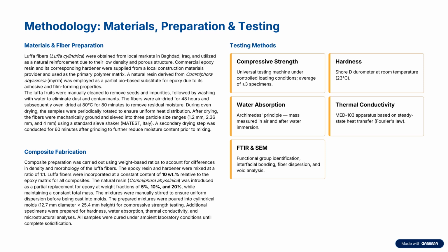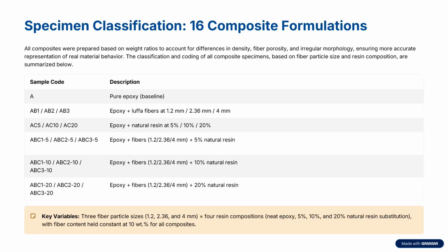Additional specimens were prepared for hardness, water absorption, thermal conductivity, and microstructural analysis. All samples were cured under ambient laboratory conditions until complete solidification. For that, we test compressive strength, hardness, water absorption, thermal conductivity, and SEM. All composites were prepared based on weight ratio to account for differences in density, fiber porosity, and irregular morphology, ensuring a more accurate representation of real material behavior.